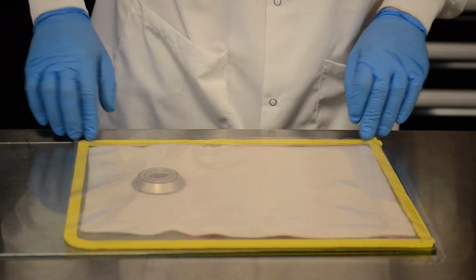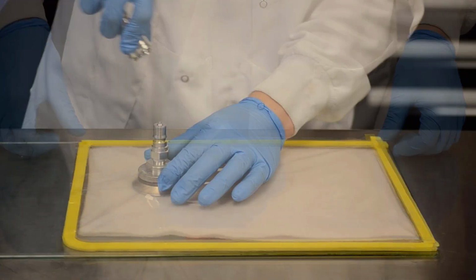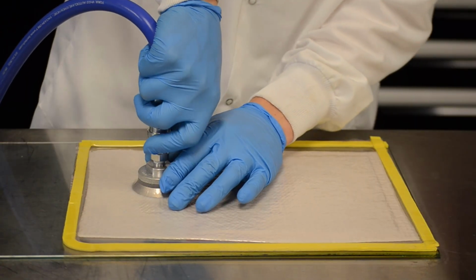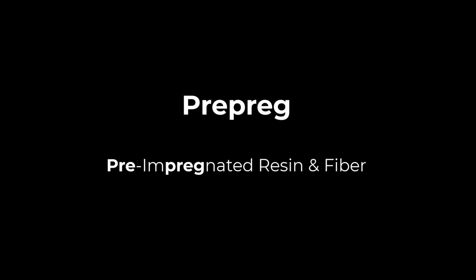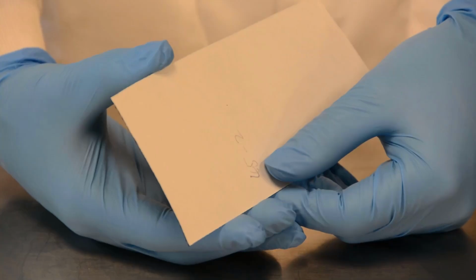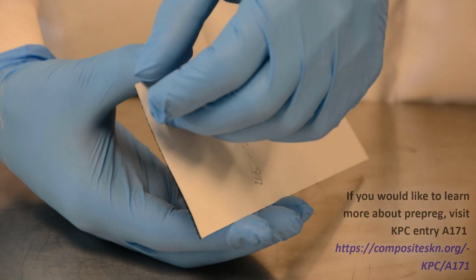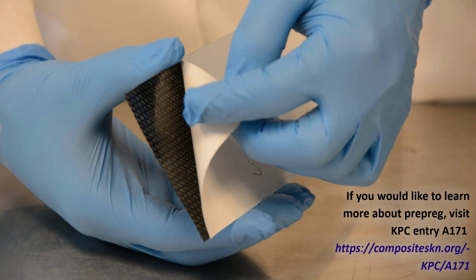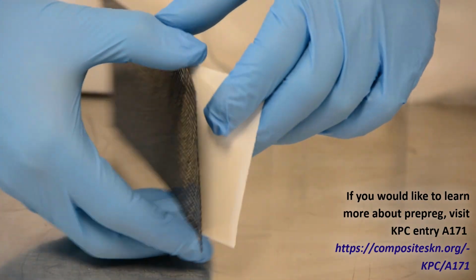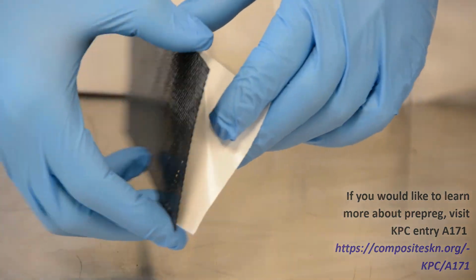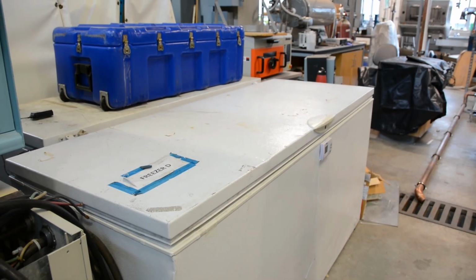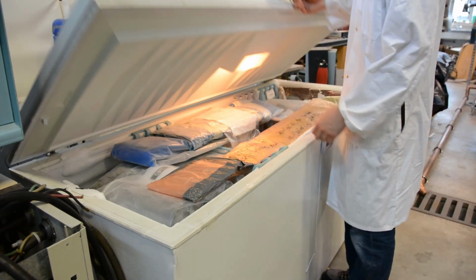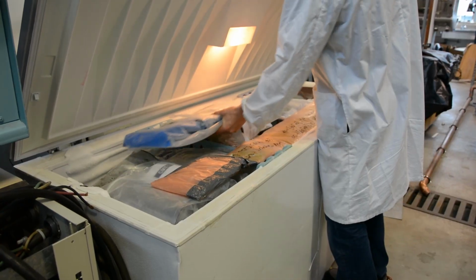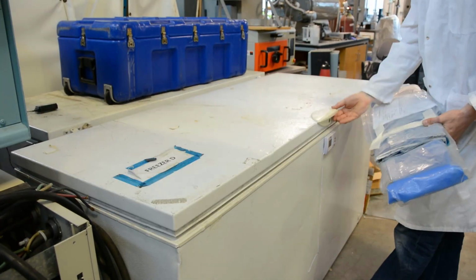After watching this video, you will be familiar with some considerations to be aware of when performing a Prepreg hand layup. What is Prepreg? Prepreg is a material consisting of fibers that have been pre-impregnated with resin. The resin is partially cured at the factory before storing and shipping at -18 degrees Celsius. Storage at low temperatures prevents the resin from further curing during storage. Resin curing progresses at room temperature, but is inhibited by low temperatures.